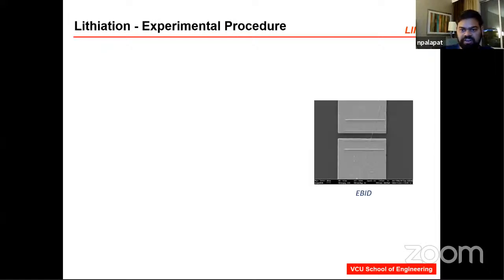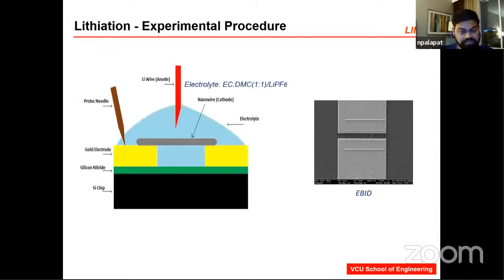So, step by step, I deposit these nanowires on the chip, as I talked about earlier. Then I mentioned this technique called EBID, electron beam induced deposition. Once all this is done, the very first step involves lithiation. The lithiation itself is done inside a glove box because lithium can explode. It's a harmful chemical. The experimental setup involves putting the chip in an electrolyte and having a lithium wire that acts as an anode, and the nanowire itself acts as a cathode. Once we apply the electrical bias needed, that will either charge or discharge your nanowire accordingly.